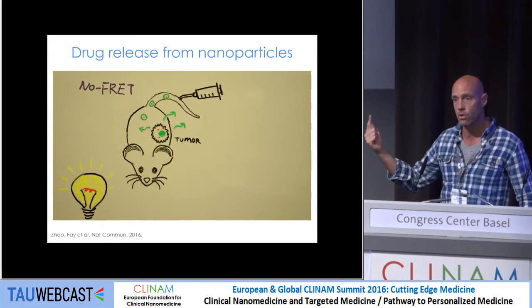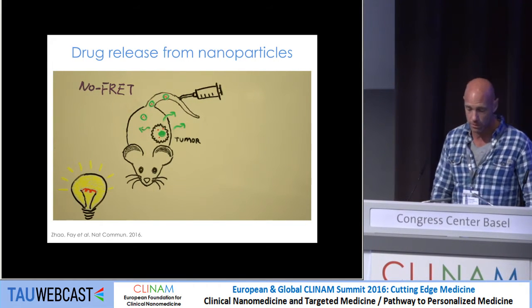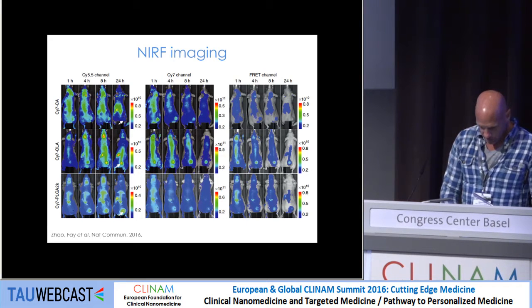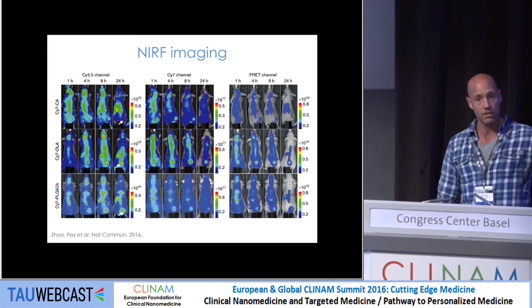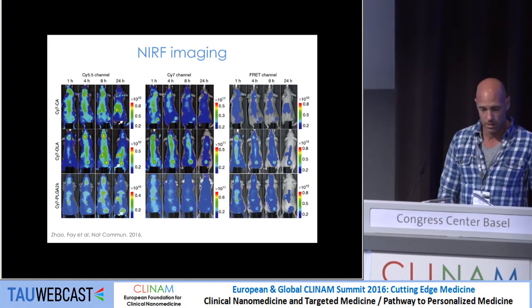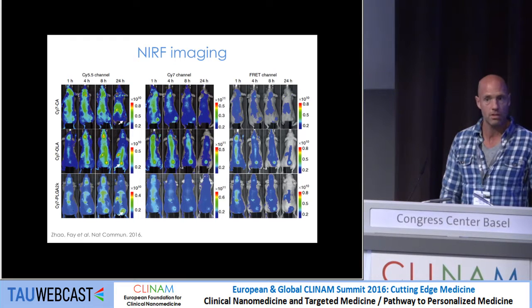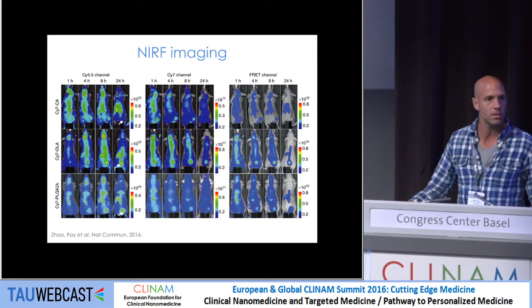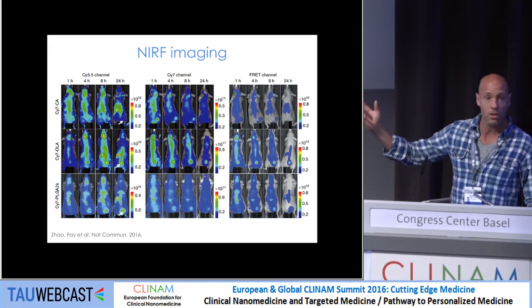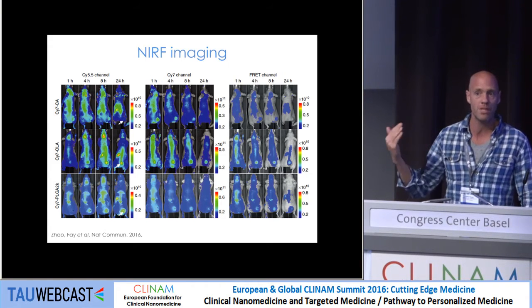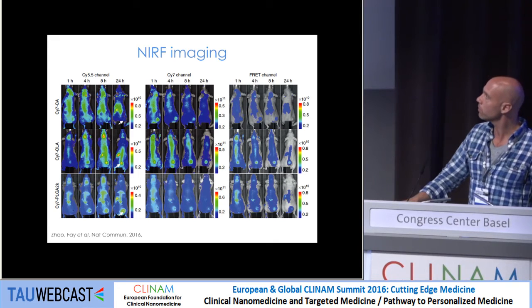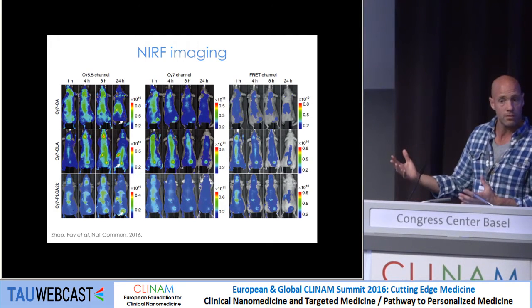This allows us to do in vivo imaging of drug release from nanoparticles using whole-body near-infrared imaging. In the FRET channel, we excite the nanoparticle and look at emission from the drug. We can look at ratios of the donor and acceptor and model how the drug releases from the particle. What we've seen is that often when we inject these nanoparticles, the drug releases immediately before it even reaches the tumors. From all these in vivo data, we derived guidelines.